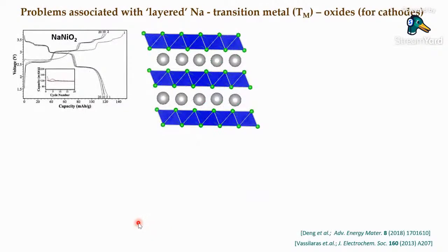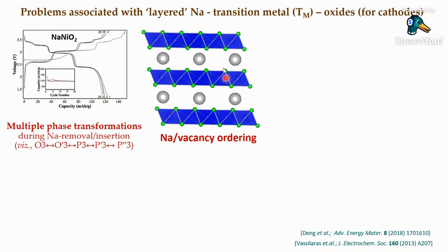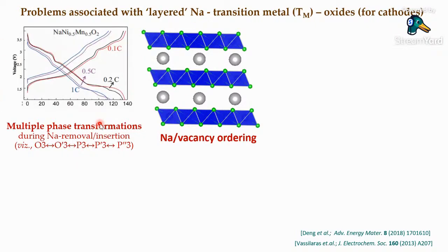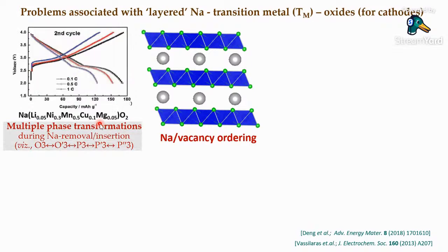So, in a nutshell, we can think of the problems associated with the layered sodium transition metal oxides as cathode material for sodium-ion battery as occurrence of multiple phase transformations and sodium vacancy ordering during sodium removal or insertion. Now, this can be addressed by multiple substitutions in the transition metal layer, leading to a smooth electrochemical galvanostatic cycling curve, the chronopotentiogram.